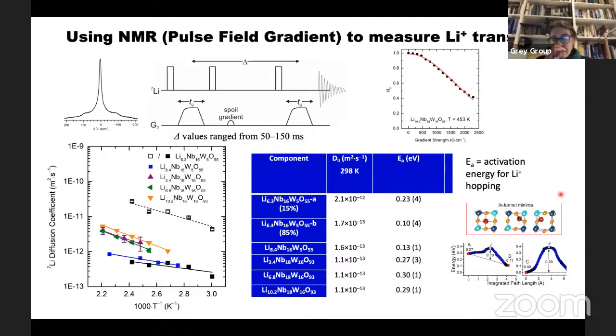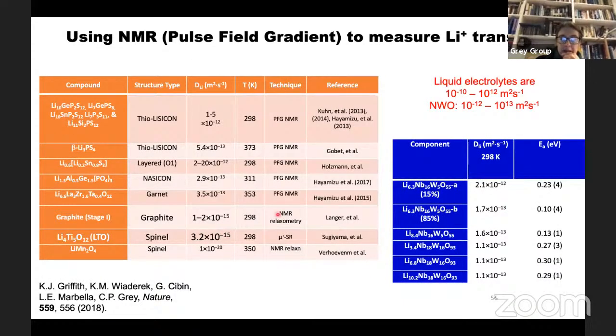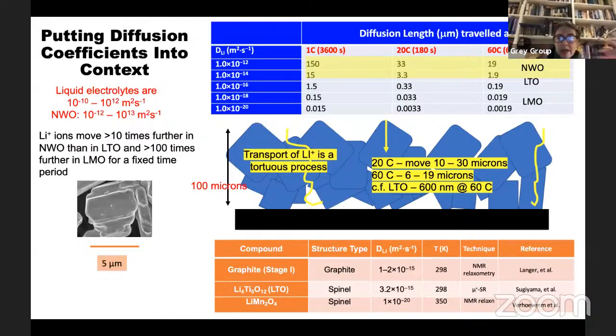And so what we then do is to ask why, and we can use a technique called pulse field gradient NMR spectroscopy to quantify how fast lithium ions move. Happy to take questions about this, but the bottom line is they move with quite low activation barriers. So I mentioned in the previous one, the activation barriers for lithium hopping in the cathode about 0.3. Here we have activation barriers that are more like 0.1 to 0.3, so lower, and relatively fast diffusion coefficients. And they're faster than the best in class solid state conductors, not as fast as liquid electrolytes, but still really good. And so that was enough to get this work into Nature and then make us think about why this happens.